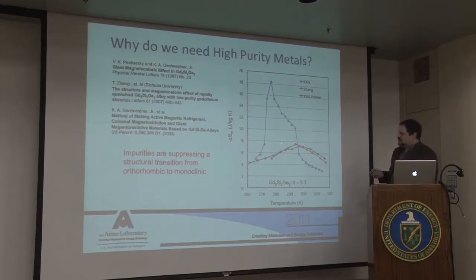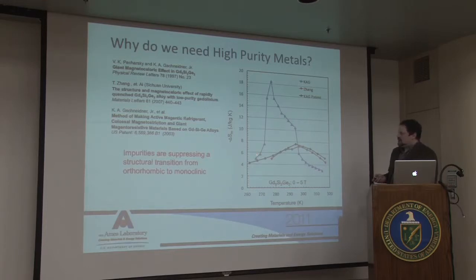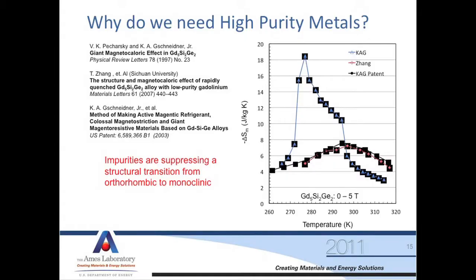Pure gadolinium actually sits slightly above these two lower humps. So you've lost all this available work. What's more important is, if this were the starting material for the research on gadolinium silicon germanium, they may never have discovered this large change. And that's what it's all about. The physicists want to know what is the true nature of this material, and the impurities may mask the true nature of the material. In this case, we're suppressing a structural change which adds to the entropy. But if you don't know what you really got, do you really understand the physics?